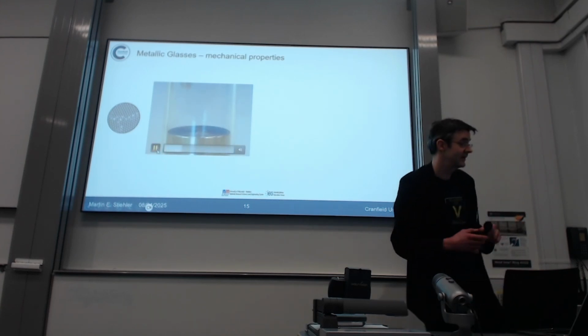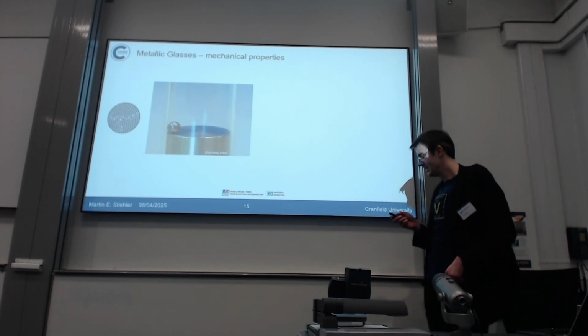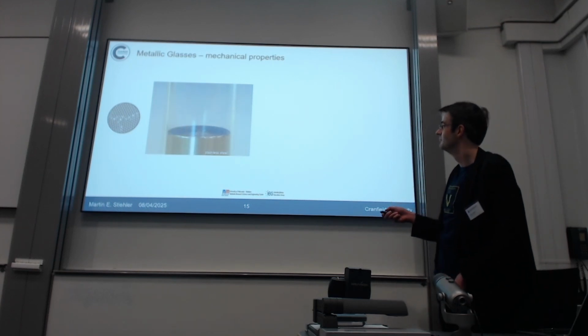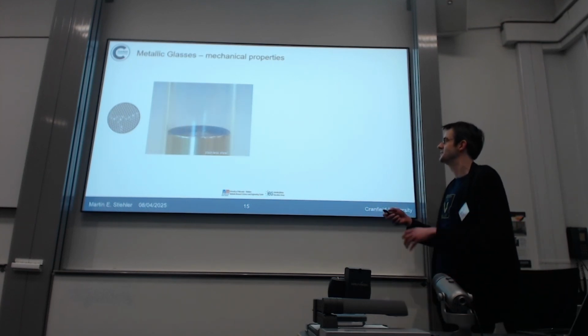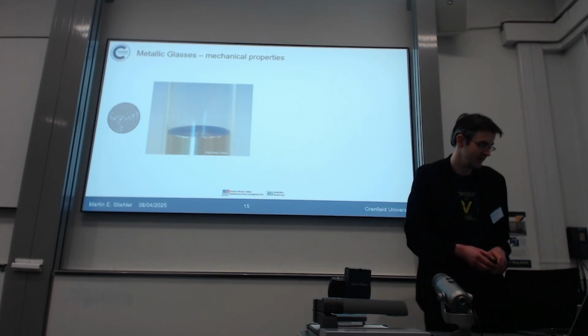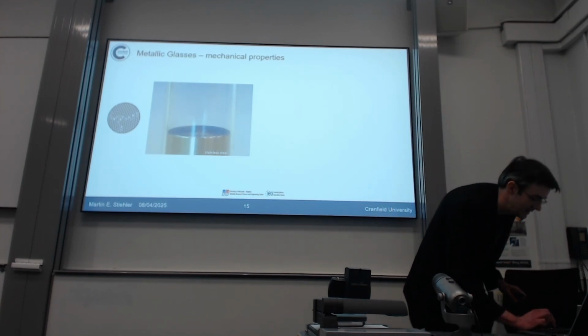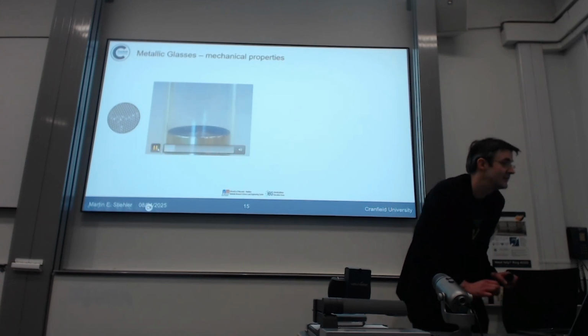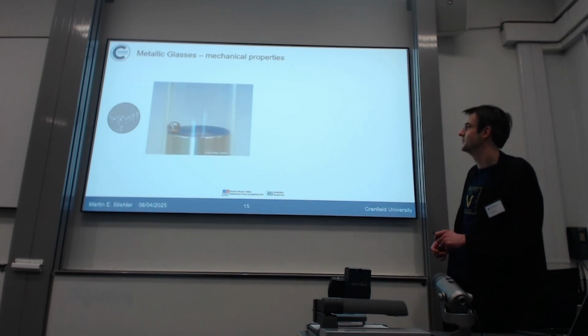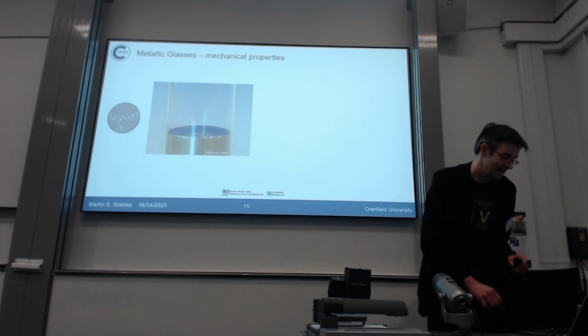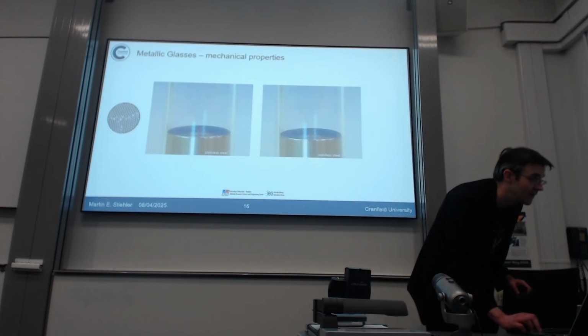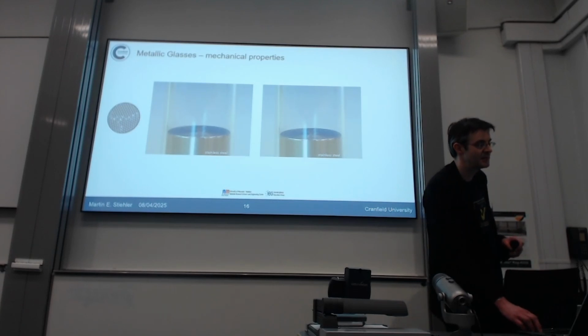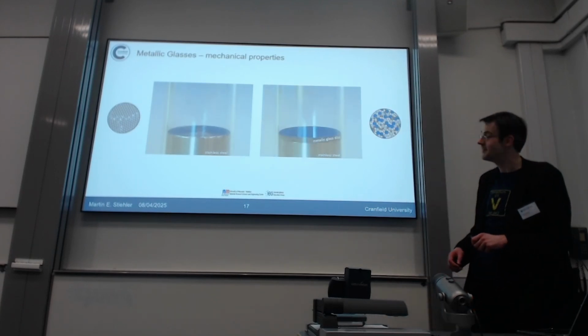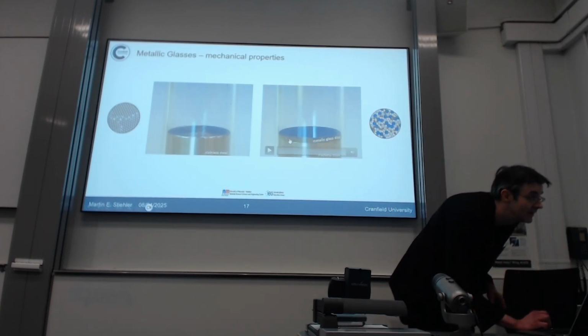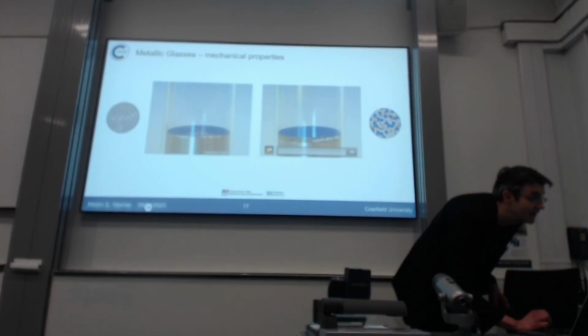So this is something very simple. There's a stainless steel column here, a stainless steel base, and you drop a ball of stainless steel there, and not unexpectedly, this ball comes to rest quite quickly because all the energy is used for plastic deformation in the ball and the stainless steel on the bottom. If you take the same thing but put a disc of metallic glass on there and repeat the experiment, we get something like this.